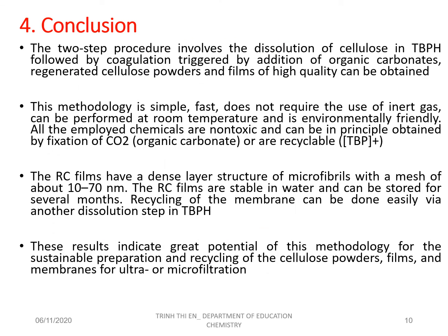In conclusion, the two-step procedure involves the dissolution of cellulose in TBPH, followed by coagulation triggered by addition of organic carbonates, to generate cellulose powder, and film of high quality can be obtained.